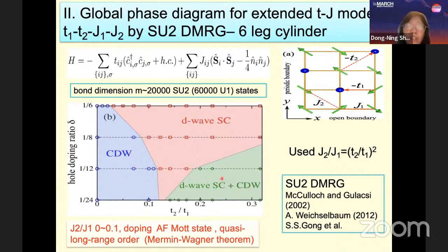So our whole phase diagram is actually based on doping the antiferromagnetic ordered state, not doping a spin liquid, which provides evidence that superconductivity is more common in such a system through doping, as long as we increase the fluctuation with the second nearest neighbor hopping and antiferromagnetic spin exchange.